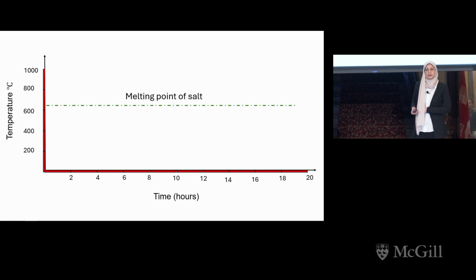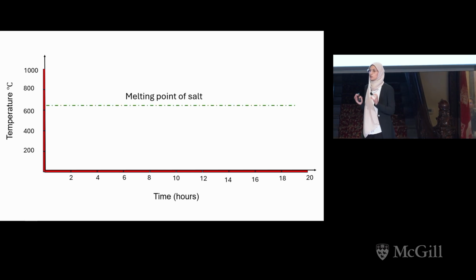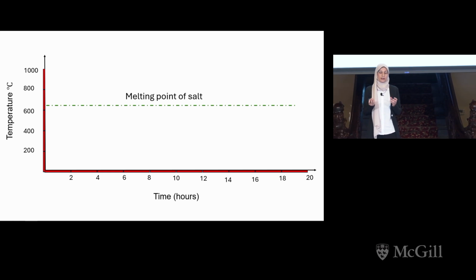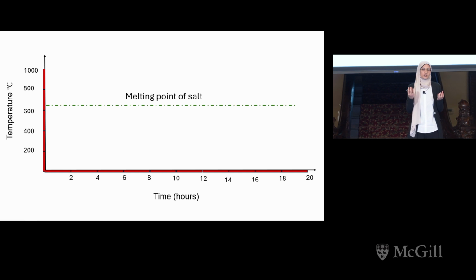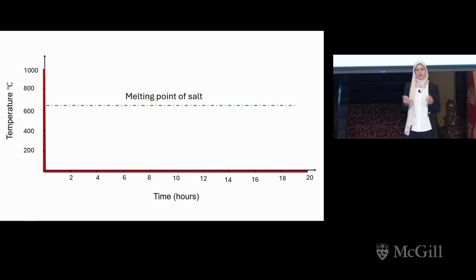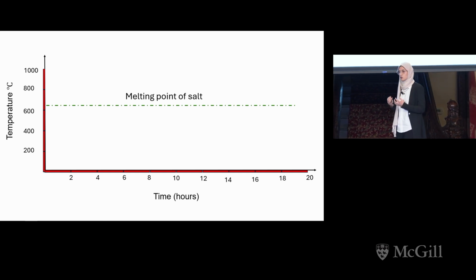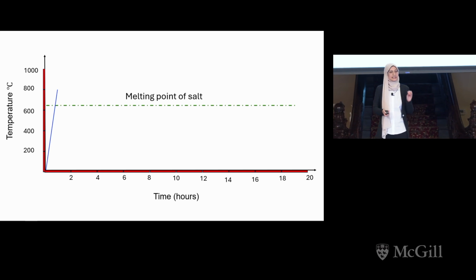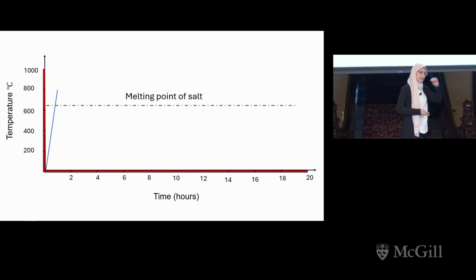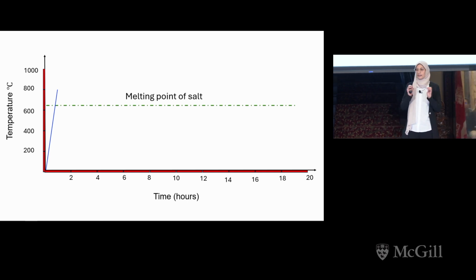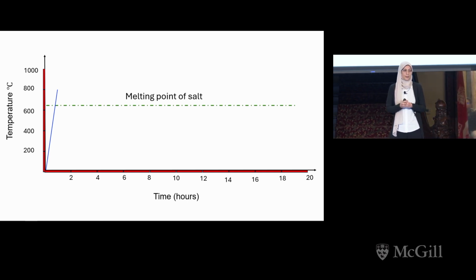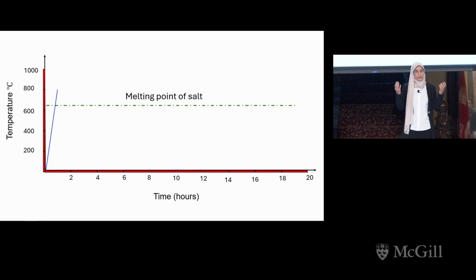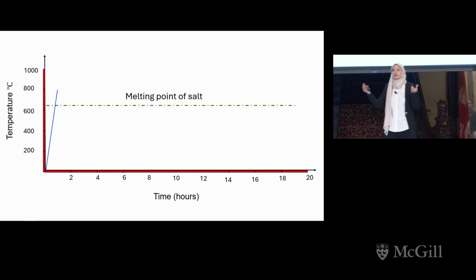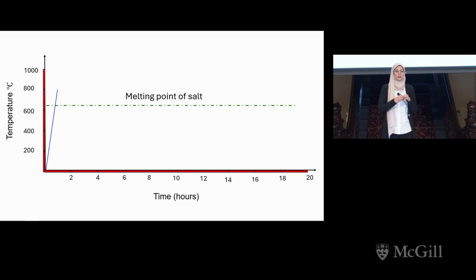In the beginning, before we start, we just mixed the solid precursor with a salt, like table salt. We will understand soon what is the function of the salt in this process. After mixing the solid precursor with the salt, we heat the mixture slightly above the melting point of the salt. So now we are above the melting point of the salt, the salt will melt and act as a liquid medium. Now the solid precursor will start dissolving in this molten salt.